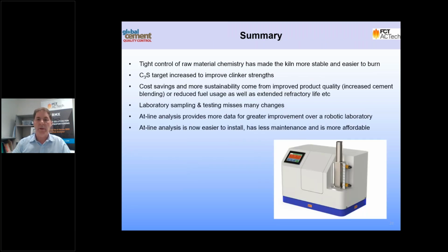So in summary, this case study has shown that using an at-line analysis of raw meal for mix control will stabilize the kiln, and the clinker will be much easier to burn. With the more stable kiln, the plant was able to choose to increase its C3S target so that it could increase strengths, something that they were never able to do before.